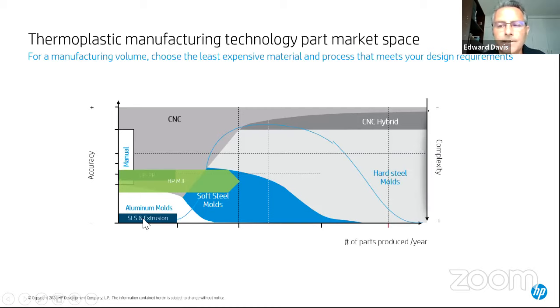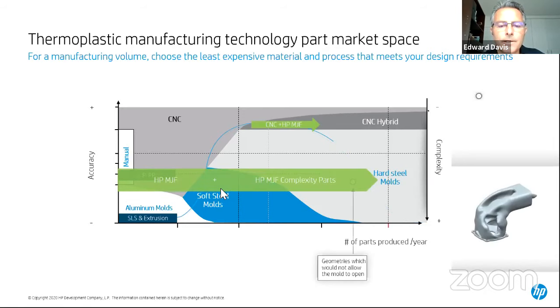Whereas we've done our own internal tests on SLS and extrusion, and they're more along the lines of IT 15-16. So what we attempt to do then is to take some market from CNC over in this zone, because we're actually more cost effective than CNC in this zone, and take some market from the parts you might get from soft steel molds right here. Now, that's for normal geometries. That's for geometries that you can mold. There's some additional things that you can do with 3D printing, which is to print things which can't be molded.